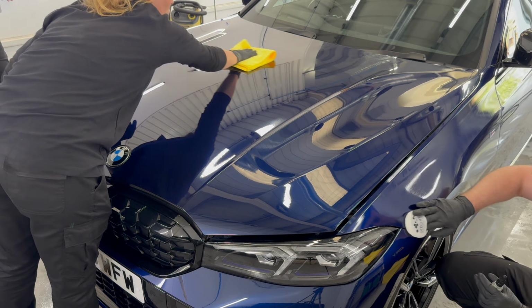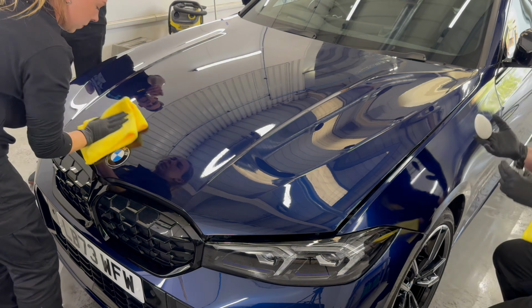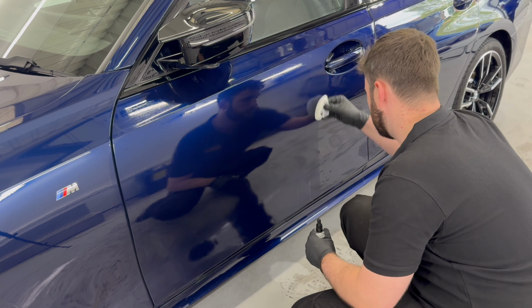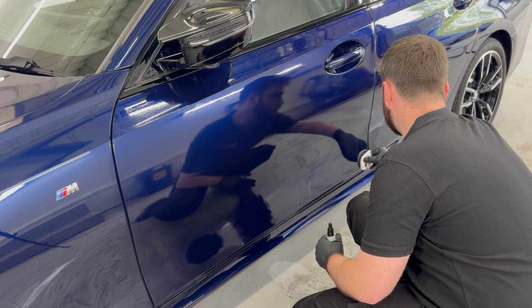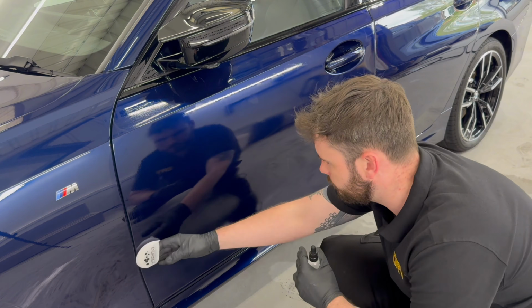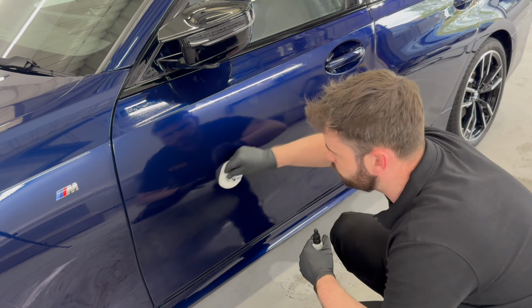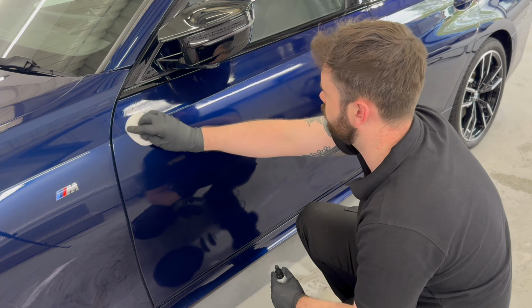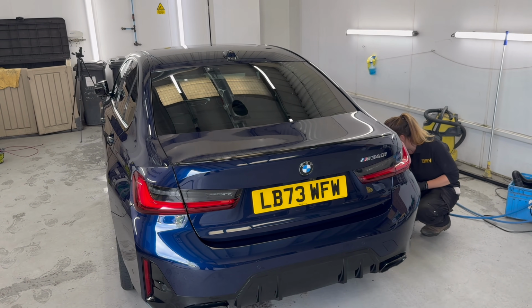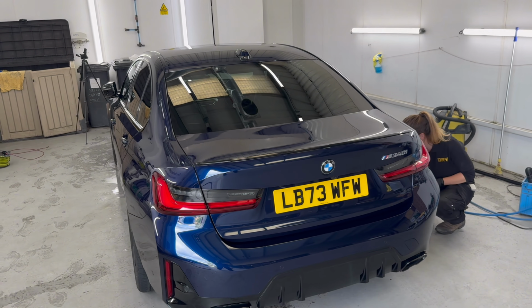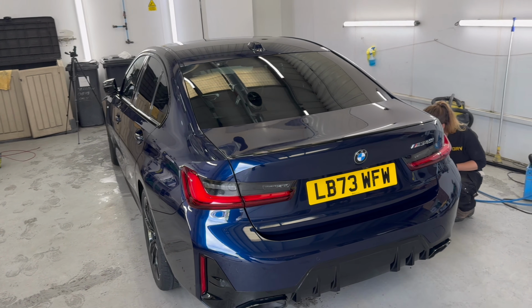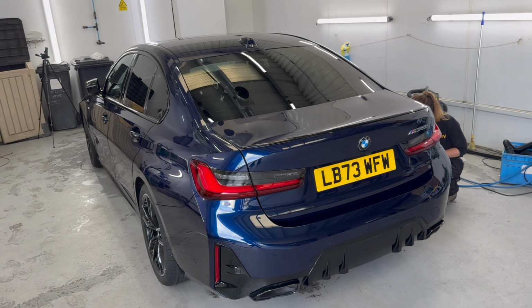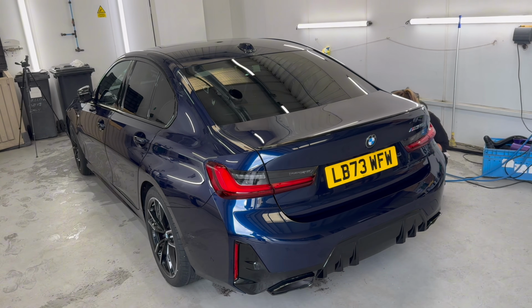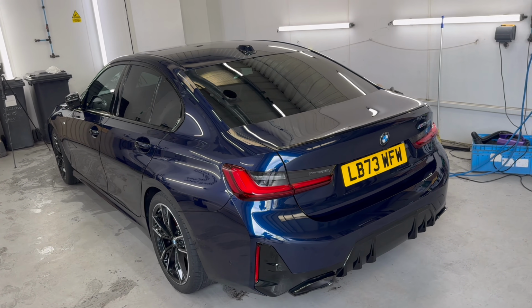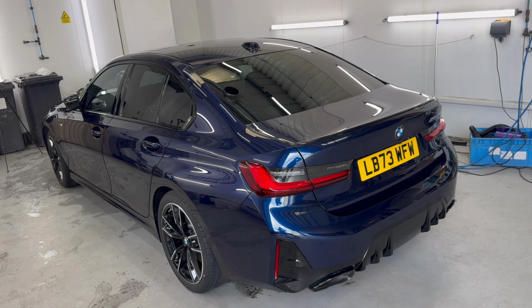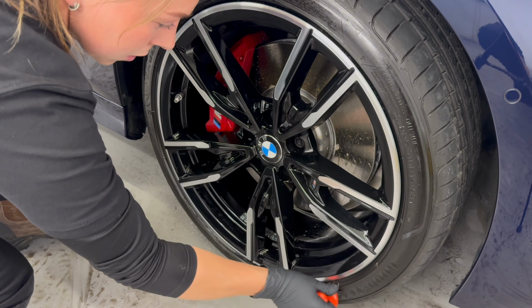It's important to remember that when you're applying a ceramic coating, the car needs to be out of the elements. If the coating is exposed to rain or water during its curing time, it can have a catastrophic effect on how well it actually bonds to the painted and plastic surfaces. If you apply the ceramic coating in direct sunlight, it can heat up the panels and cause premature flashing, which causes the same defects that I've already discussed when you leave the ceramic coating to cure or flash for too long. And finally, if you're not applying a ceramic coating in a controlled environment, you run the risk of dust and airborne debris landing on the wet film and becoming trapped.